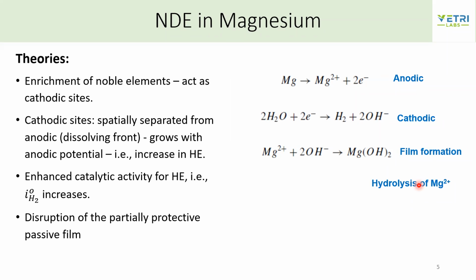So for the NDE in magnesium, it is because of two important factors. One is magnesium is a very active metal. If we look at the EMF series, magnesium is much more active than many other metals. So if we consider pure magnesium, it's going to have impurities such as iron or other metals embedded in its surface. Since magnesium undergoes high dissolution, these noble elements tend to enrich on the surface and start acting as cathodic sites. And once they start acting as cathodic sites, they basically support hydrogen evolution. This is one reason that people think is responsible for the NDE.